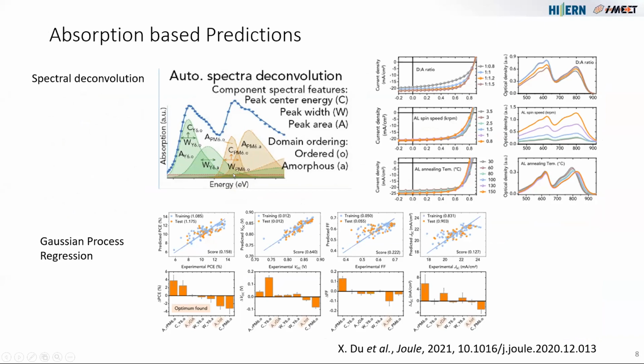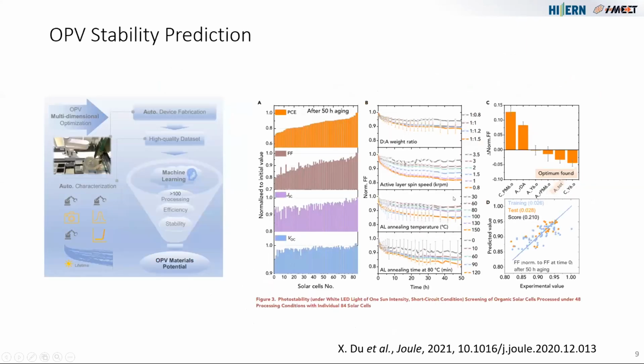where we were using the PM6Y6 system, and fabricated 50 to 100 devices under different donor acceptor ratio, different spin speeds, different annealing temperatures, always measured the IV curve and the absorption. And then, so this was done by Xiaoyan, and then Larry was basically extracting features from these absorption spectra and correlated them to device efficiency. So that now at the moment we can almost just from the absorption spectrum predict how efficient a solar cell will be. The next step was to apply the same method for stability data.